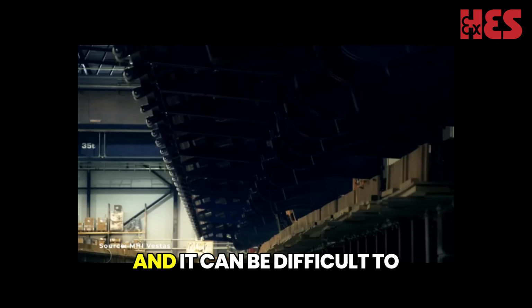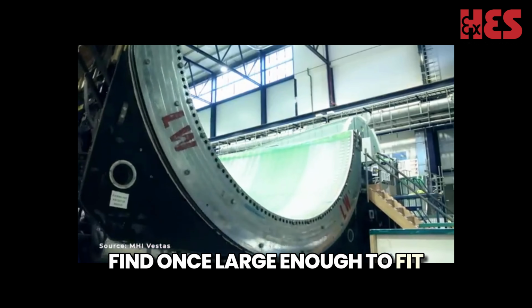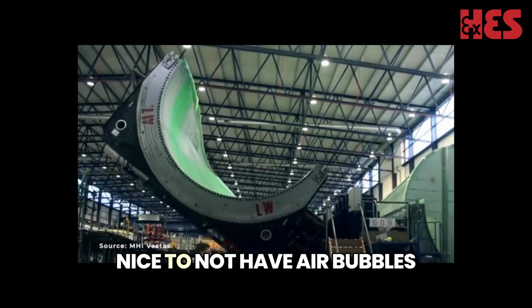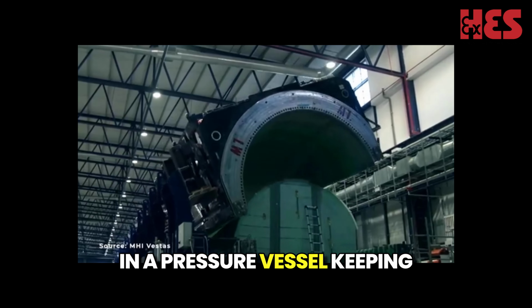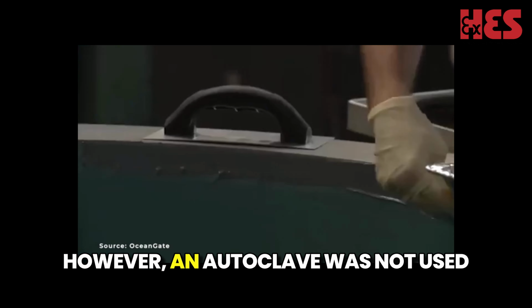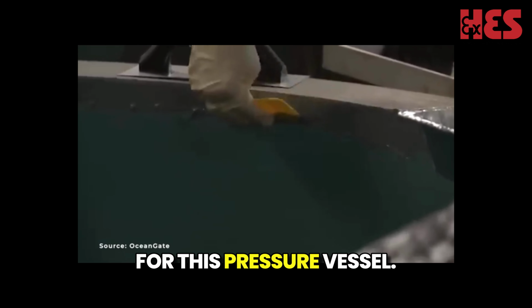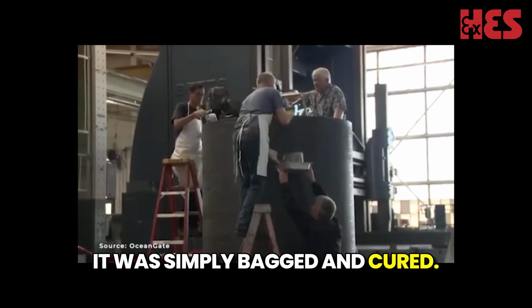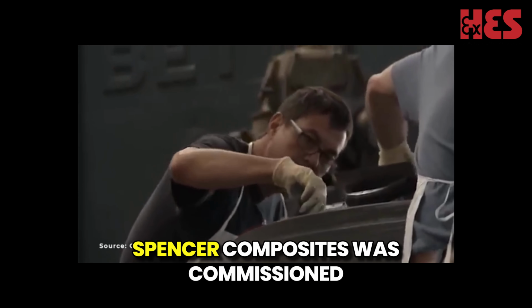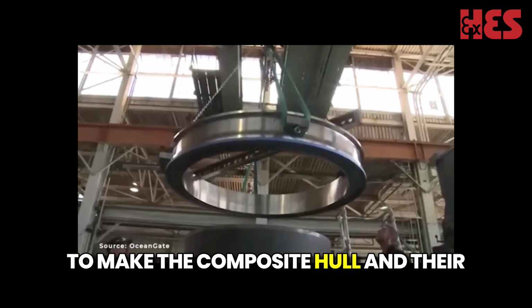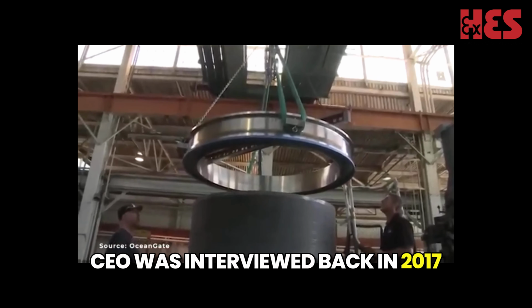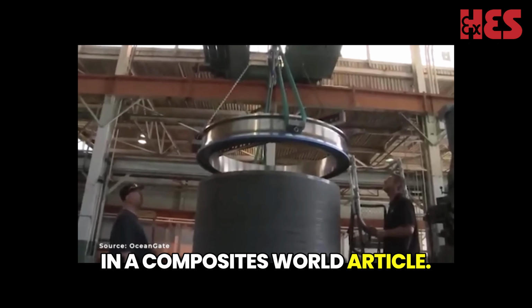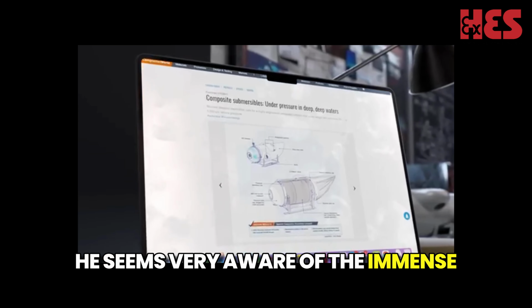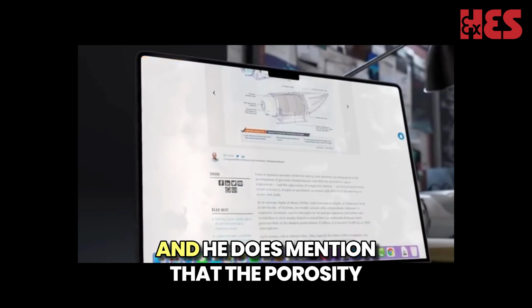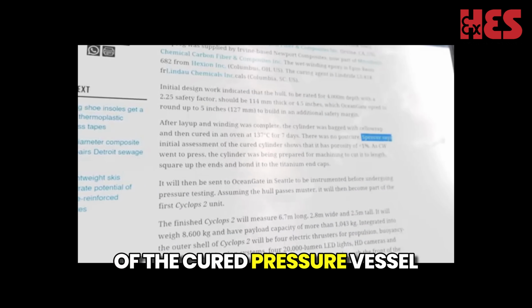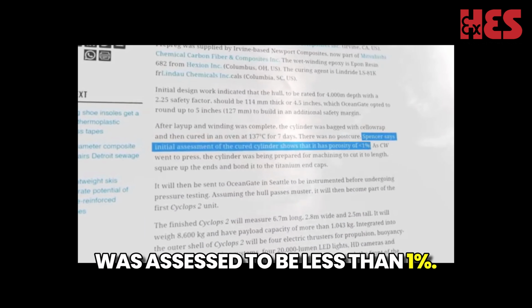Autoclaves are expensive, and it can be difficult to find ones large enough to fit something like this, but it's nice to not have air bubbles in a pressure vessel keeping you alive. However, an autoclave was not used for this pressure vessel. It was simply bagged and cured, a cheaper alternative. Spencer Composites was commissioned to make the composite hull, and their CEO was interviewed back in 2017 in a Composites World article. He seems very aware of the immense design challenge he has been handed, and he does mention that the porosity of the cured pressure vessel was assessed to be less than 1%.